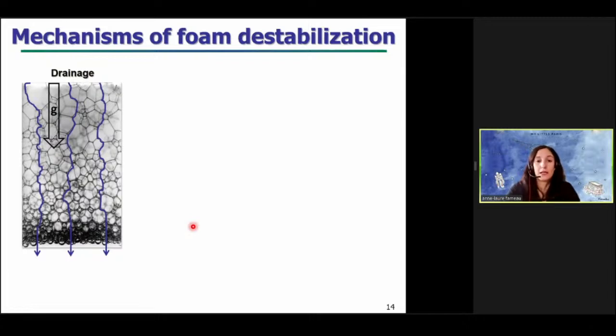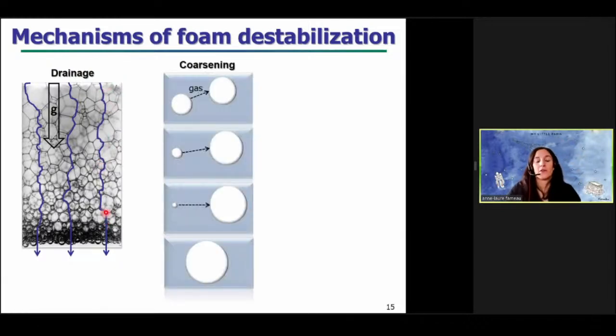The main problem with the foam is that it is an unstable system that tends to destabilize with time under three main mechanisms of foam destabilization. The first one is called drainage. It's due to gravity. Due to gravity, the liquid flows through the foam from the top to the bottom, and the result is a dry foam. The second one is called coarsening. When you have two bubbles, the smaller bubble transfers its gas to the bigger one due to the difference of Laplace pressure between the smaller and the bigger bubbles. And the result is a disappearance of the smaller bubbles, and so you have an increase of the bubble size with time.